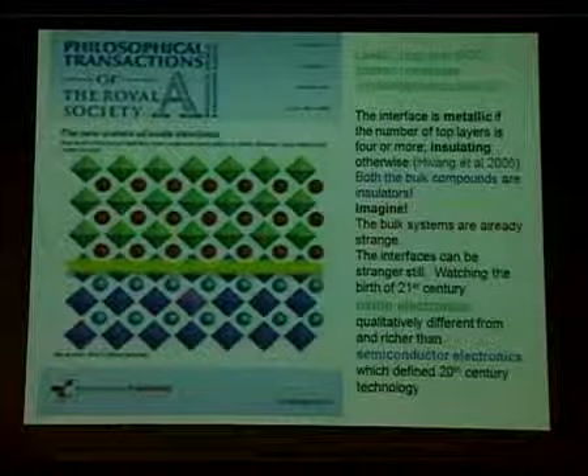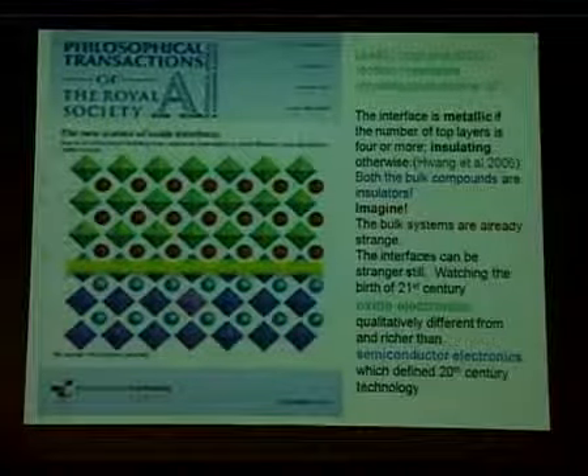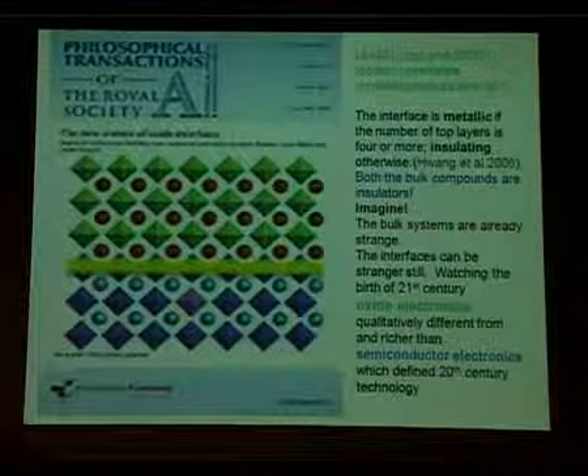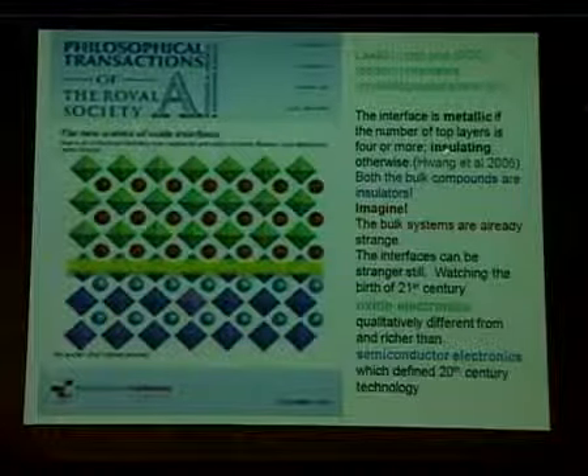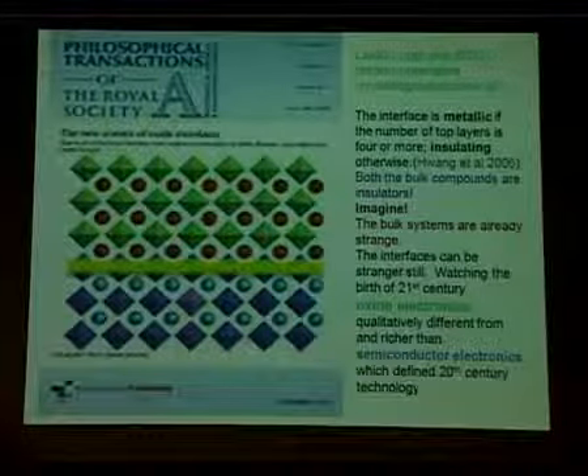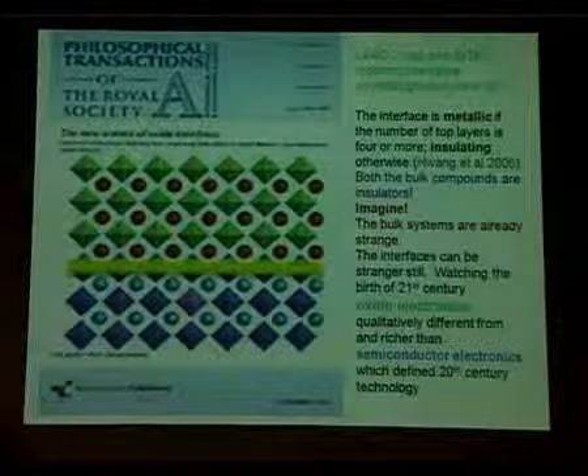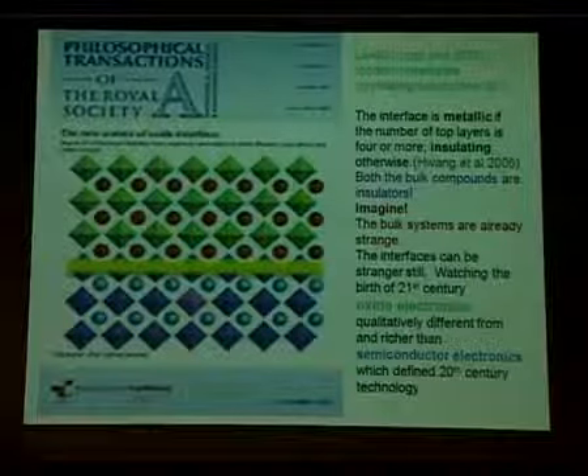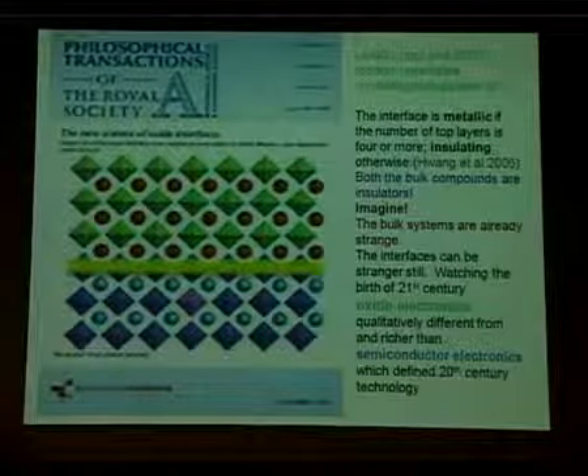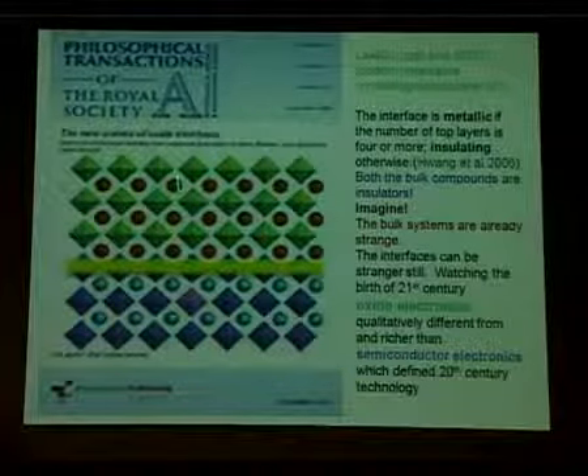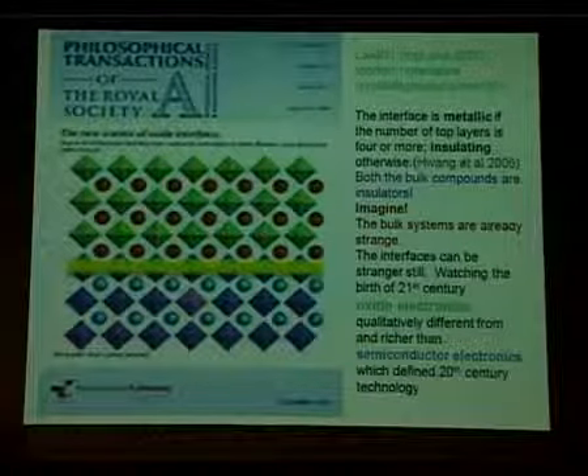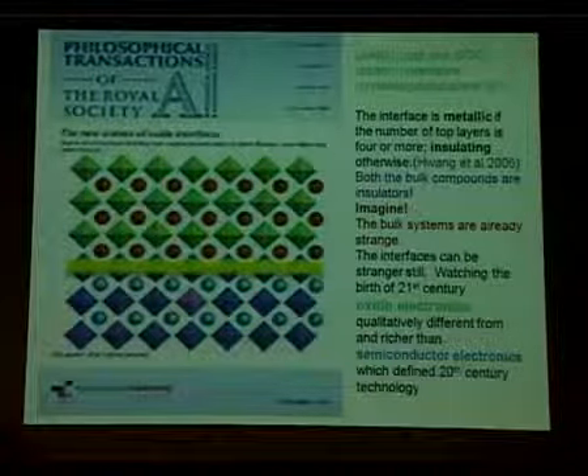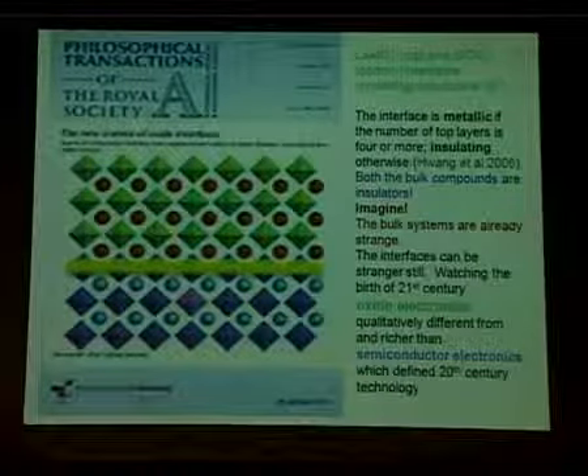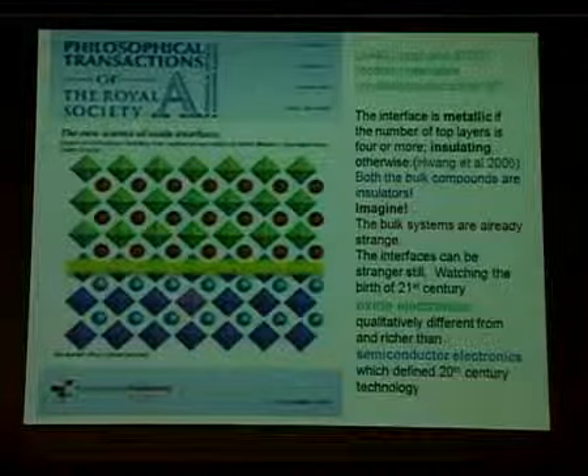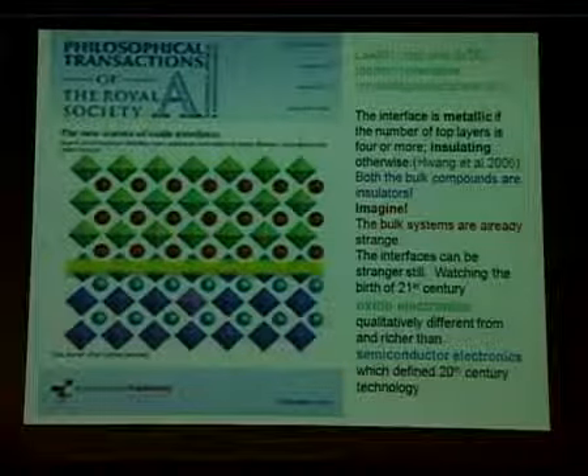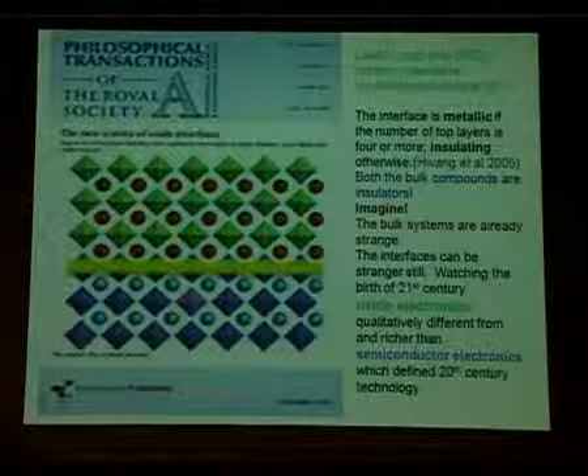So now the excitement is the following. About 6 years ago, some physicists, Hwang and others, put together layers with a particular crystallographic orientation, 001 orientation, of strontium titanate, which is at the bottom, and lanthanum aluminate, which is at the top. And this is not a trivial thing, because putting together atomically perfect layers of transition metal oxides has taken this long. It's a very difficult enterprise.